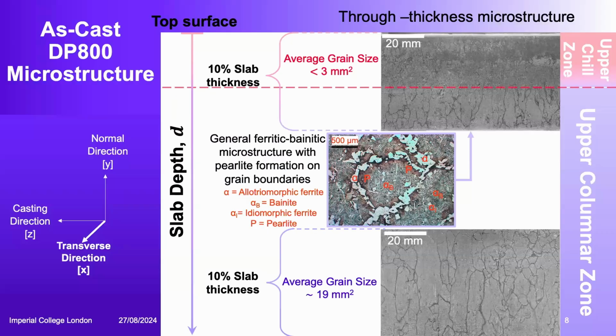Before looking at the fracture toughness properties, it was important to observe the extent of the solidification zones that I've just discussed. Some metallographic work was conducted, and quite a large area of a DP800 steel slab was polished and etched to see the extent of the solidification zones. The transition between the chill zone and the columnar zone here is quite clear in the top picture. As you can see, quite small grains, less than 3 millimeters squared, making way for quite large columnar grains, which are aligned.